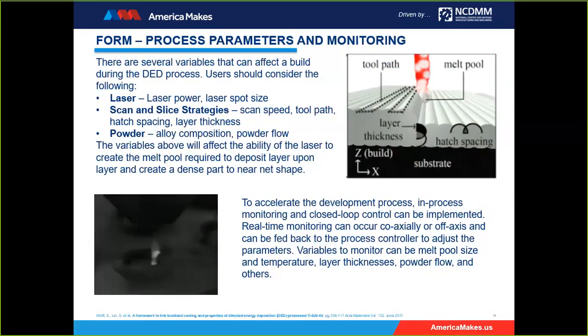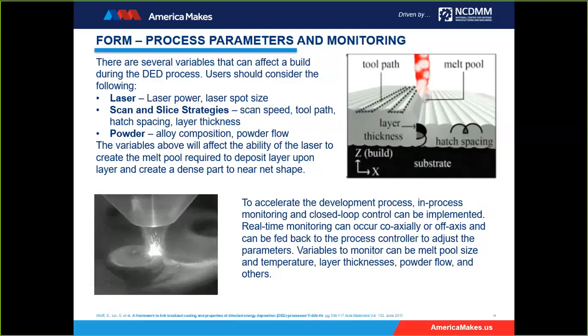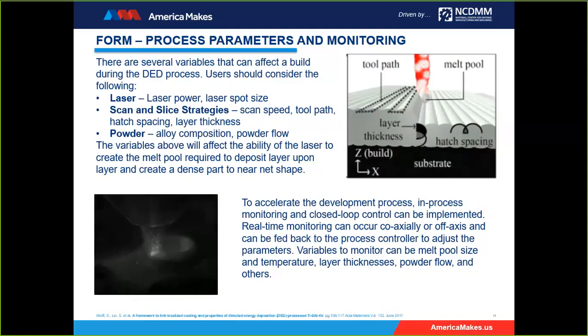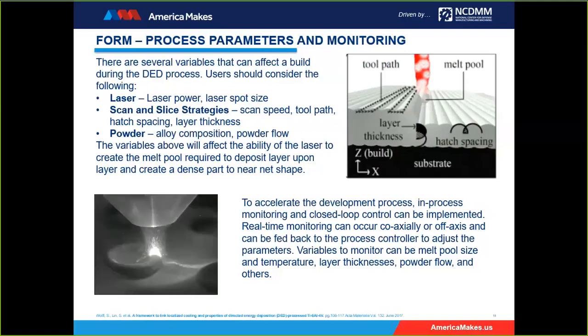And you can incorporate a variety of beam spot sizes based on the optics or the fiber configuration within the laser assembly. The scan and slice strategies can determine how accurate the features come out, the porosity within the final part, and the residual stresses within the part. And of course, the powder, when it comes to composition and powder flow, could certainly play a major part when it comes to the printability of the part.